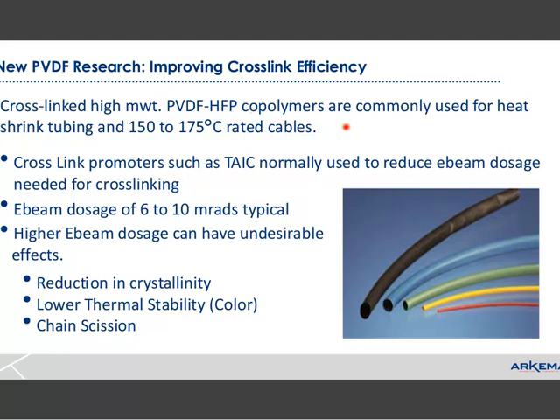For those not familiar with cross-linking of PVDF resins, normally a promoter such as TAIC, which is triallyl isocyanurate, is normally used as a cross-linking agent. E-beam dosages of 6 to 10 megarads would be typical.